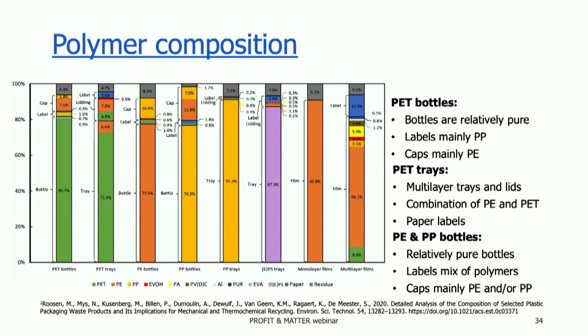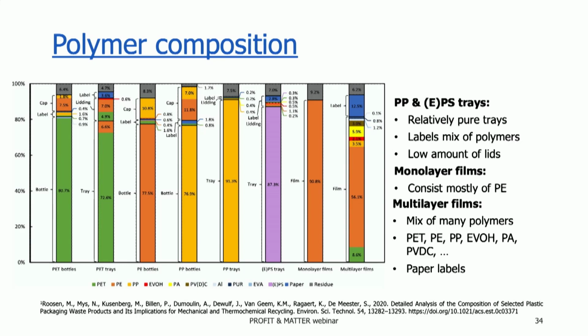The PE and PP bottles were relatively pure streams again, but also here labels and caps with a composition like polyethylene and polypropylene can contaminate these streams. For the trays, we saw that relatively pure streams were obtained for PP and EPS, but again, labels and liddings can contaminate these streams.